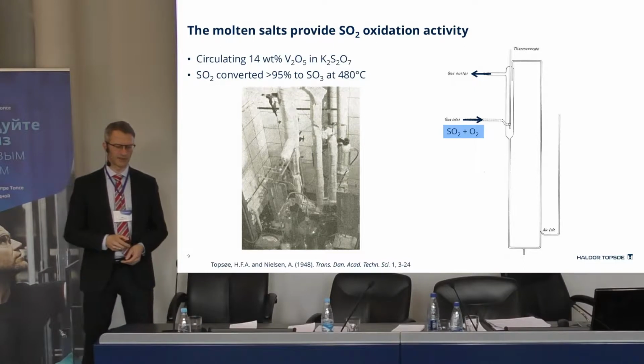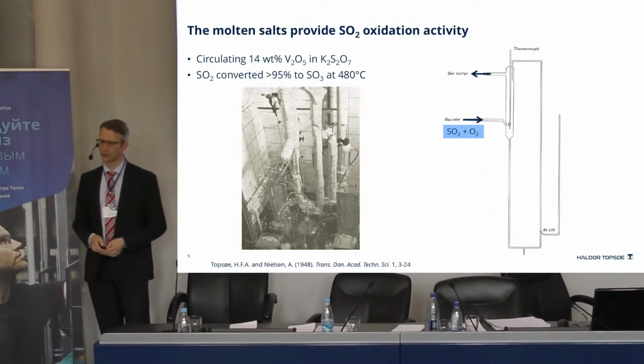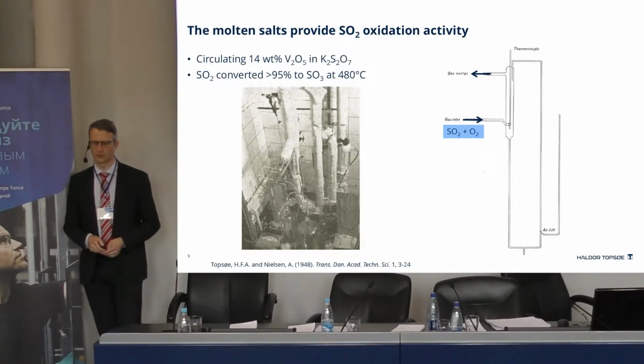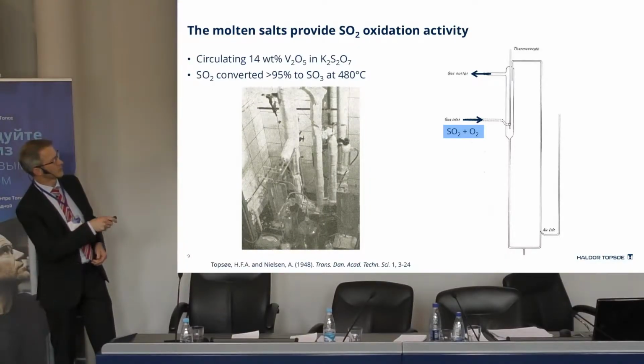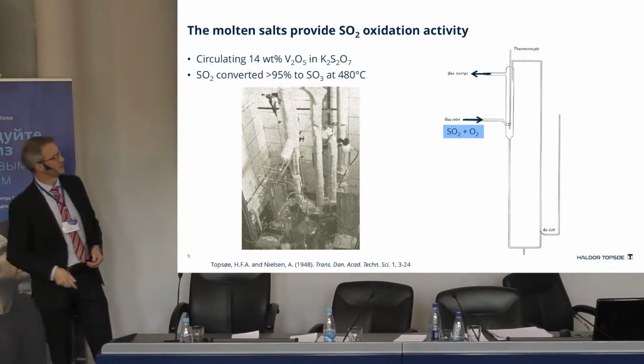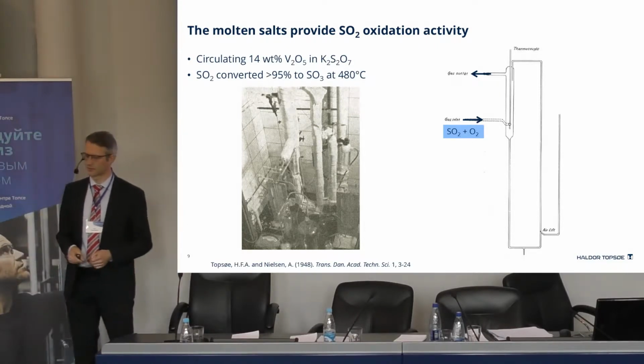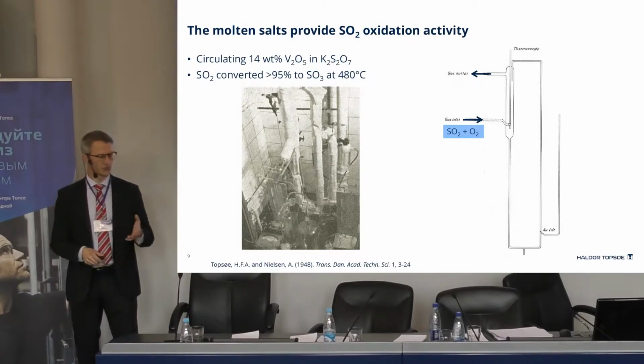This has been known for many years, and it was also shown conclusively by Haldor Topsoe himself and co-workers in 1948. They did this experiment, and you can see this old school equipment here, where they circulated in this setup 14% weight vanadium pentoxide and potassium pyrosulfate. They fed SO2 and oxygen to the setup, and they saw a very high degree of conversion to SO3 in this, showing that the carrier itself contributes to disperse the melt, but the silica is not part of the catalytic reaction as such.